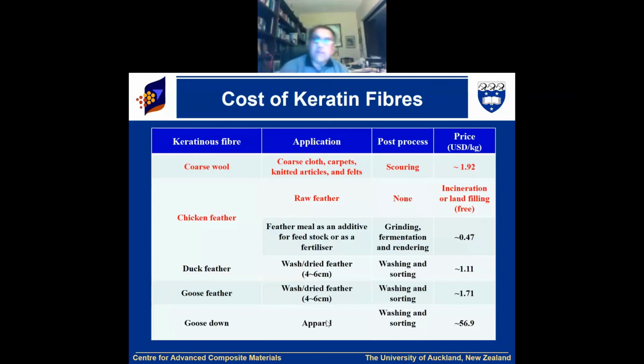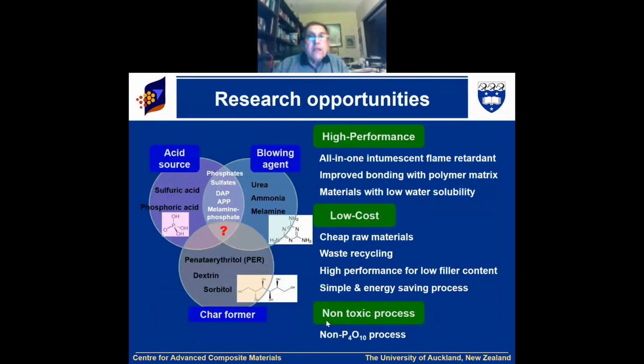In fact, we have put a price there, but sometimes you can get it free because they want to get rid of them. And so chicken feather, we thought whether we could work with them, because if we can use keratinous fiber, we add acid source, phosphoric acid we use very much, and blowing agent and char former. If we add together, then we notice that yes, the fibers get converted into very brittle fibers and coated. And what happened, in fact, then you can even pulverize it to get in powder form. So it is a non-toxic process, it is low cost and high performance.